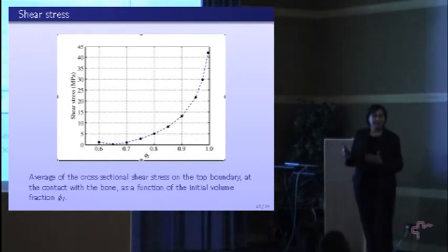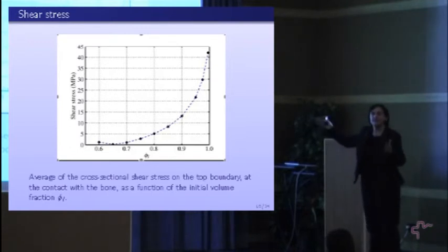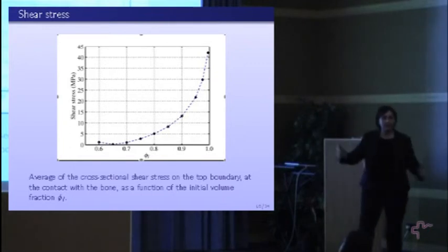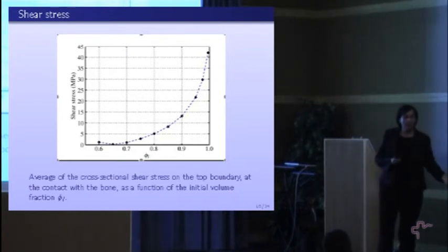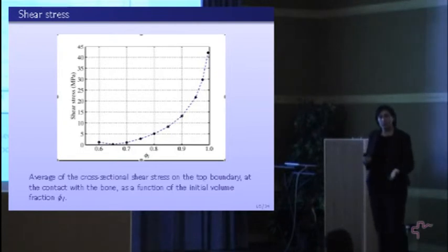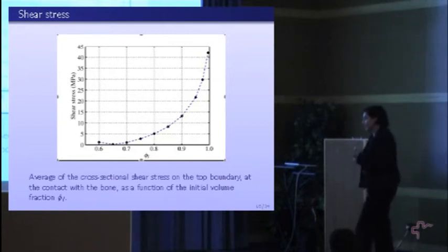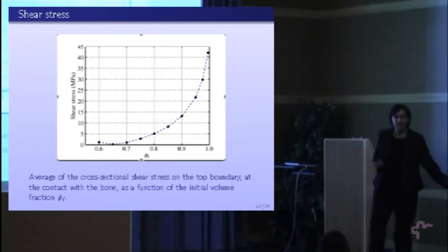Every experiment takes a year, because really this is not an equilibrium process. So through the life of the device, those stresses are going to change, so they measure over the year what happens with the stresses. So every experiment has a cost of about $1 million. So it's a lot of money that goes into determining the right kinds of materials for these implants. So what we did with the mathematical model is, out of these 20 combinations of materials, we eliminated 15. From the mathematical model, we predict that 15 are going to have stresses that are actually too big.